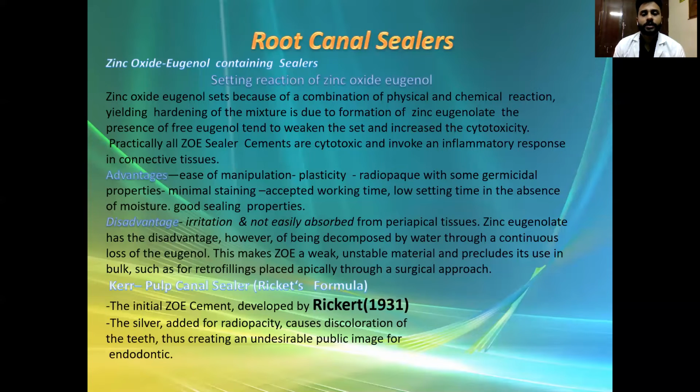Setting reaction of zinc oxide eugenol sealers. Zinc oxide eugenol sets because of a combination of both physical and chemical reactions, yielding hardening of the mixture due to formation of zinc eugenolate, and the presence of free eugenol tends to weaken the set and increase the cytotoxicity. Typically, all ZOE sealer cements are cytotoxic and invoke an inflammatory response in connective tissue.